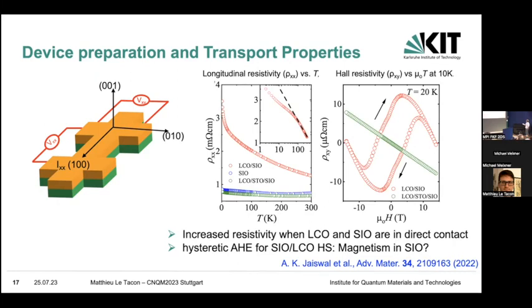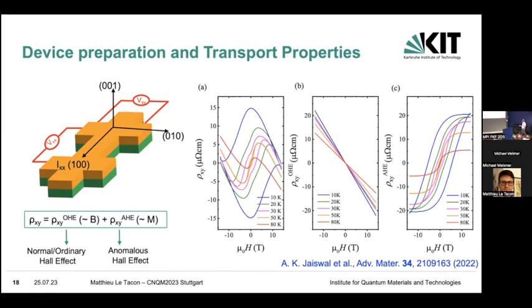But what's more surprising is if you look at the Hall effect, the transverse conductivity. What you see is that when LCO and SIO are not in direct contact, you do have the normal electron-dominated Hall effect. But when LCO and SIO are in direct contact, you now see a strong hysteresis that appears and which arises from an anomalous Hall effect, which is telling us that the charge carriers in the SIO layer are magnetically polarized. So we can look at it as a function of temperature, separate the ordinary Hall effect from the anomalous Hall effect, and we see these beautiful, essentially magnetization curves, which disappear at about 80 Kelvin when the lanthanum cobaltate layer becomes non-magnetic.